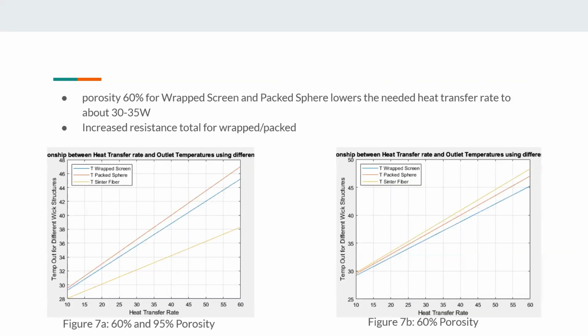For the next step, I changed the porosity for the wrapped screen and the packed sphere to 60%, which gave us a lower heat transfer rate needed to get the higher temperature. It was about 30 to 35 watts that was the best that could be done at that moment. For figure 7A, I kept the sintered fiber at 95% to show the difference between the two. For figure 7B, I chose 60% porosity for all of the wick structures, and all of them are relatively close to 30 to 35 watts. The sintered fiber was closer to 35 to 40 watts.